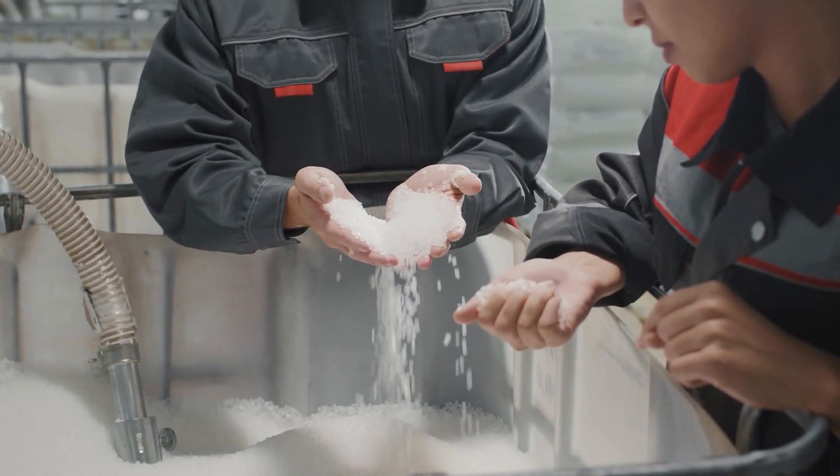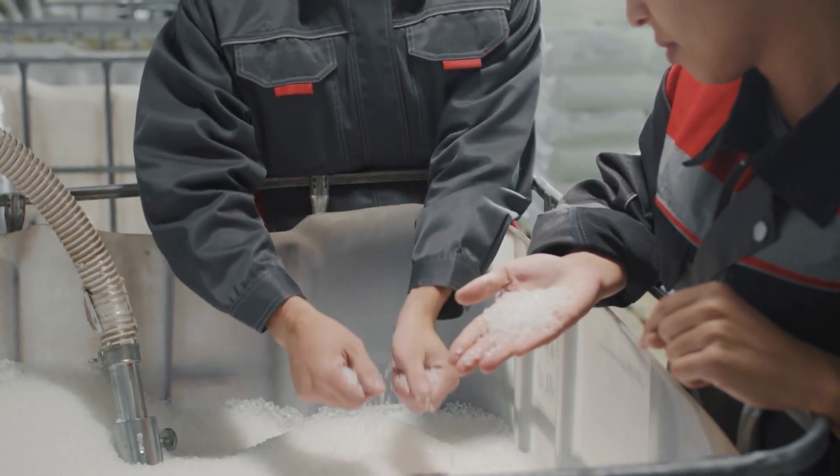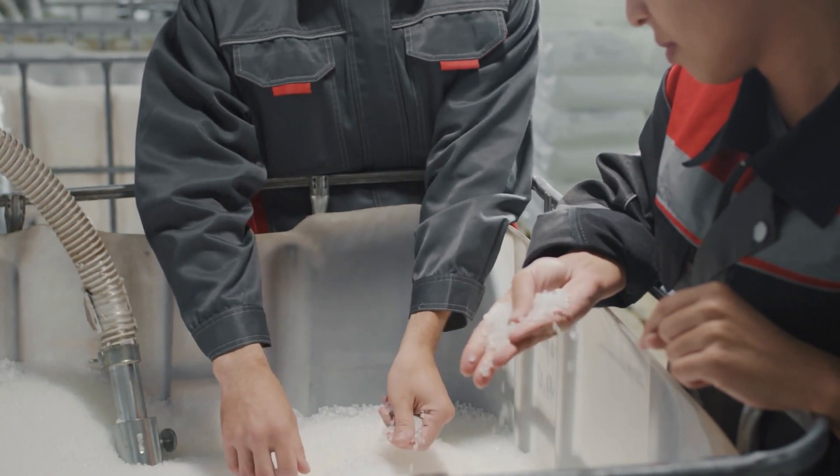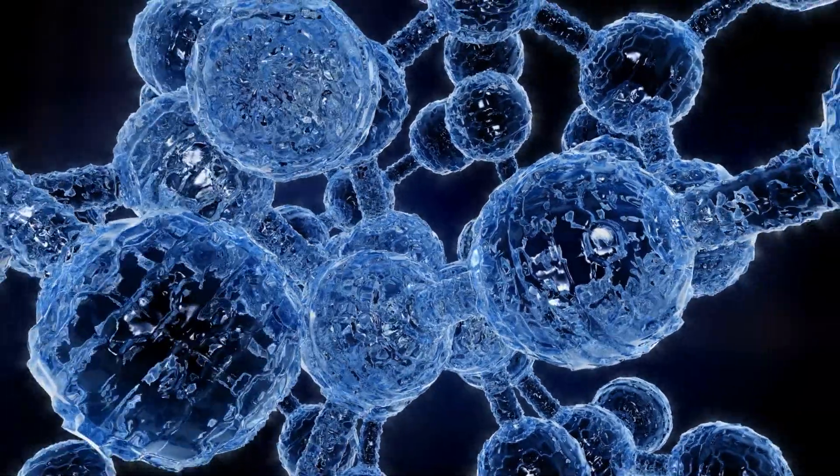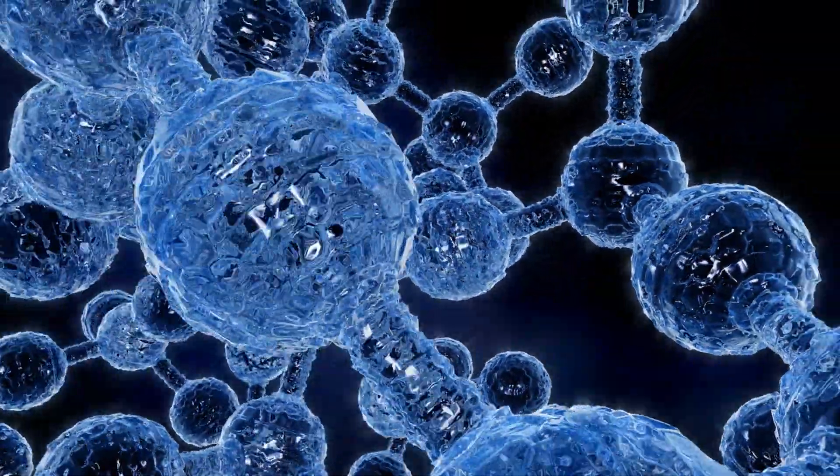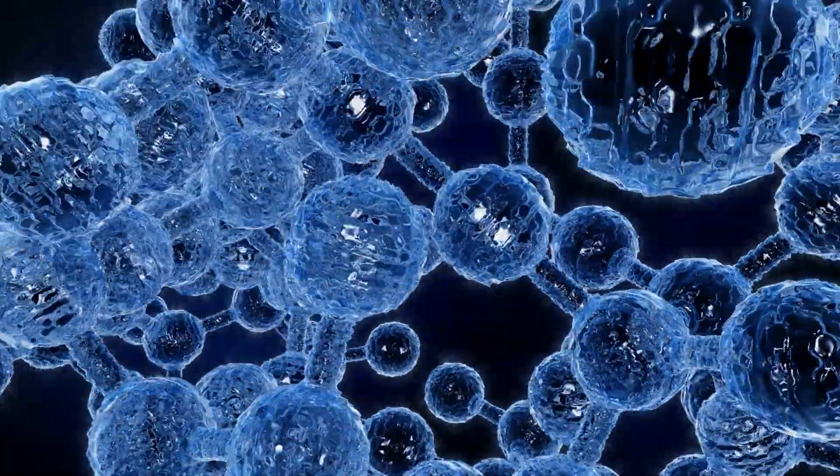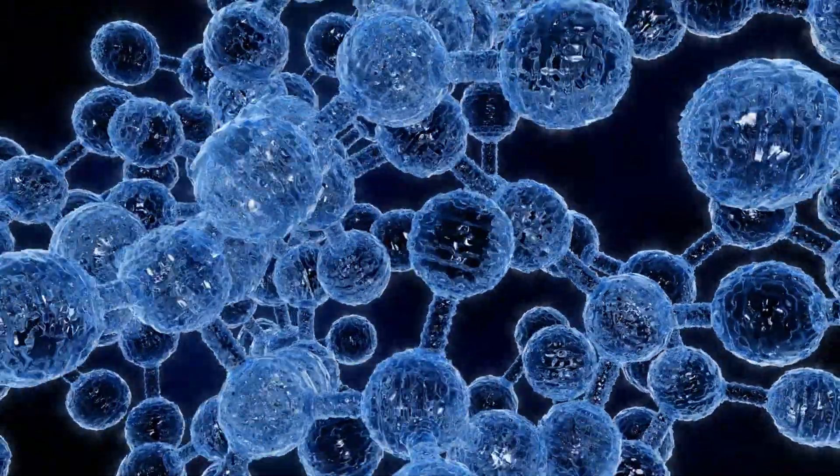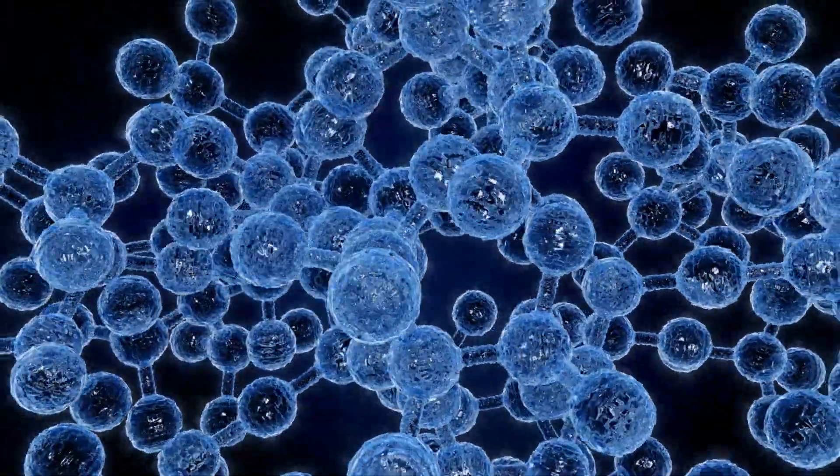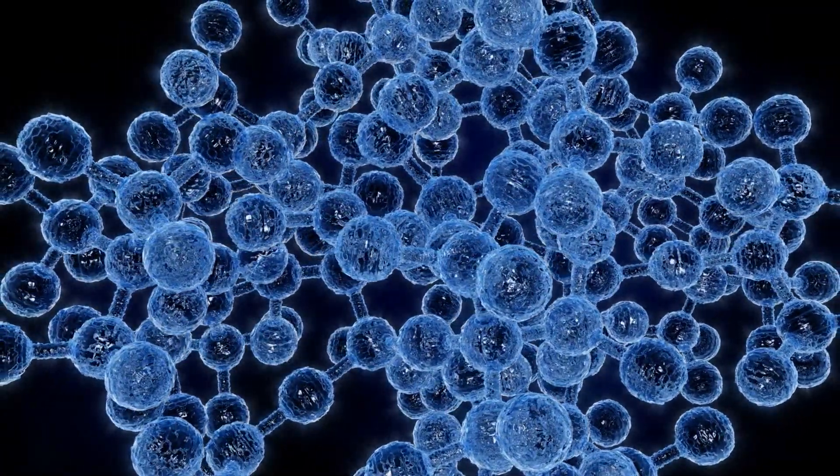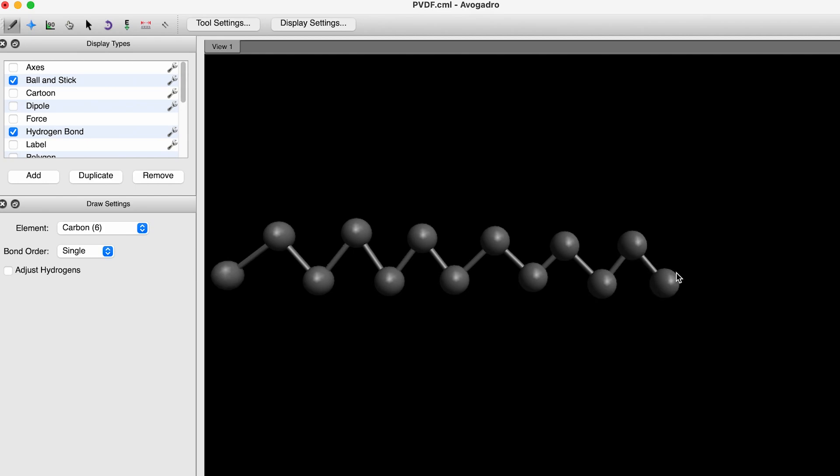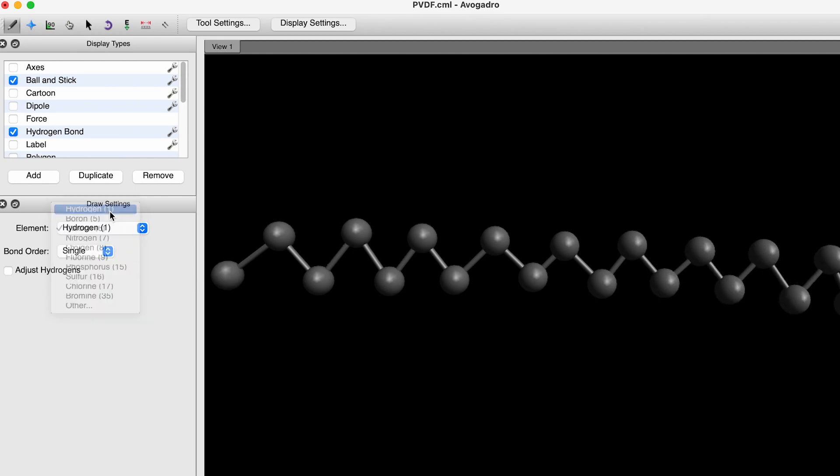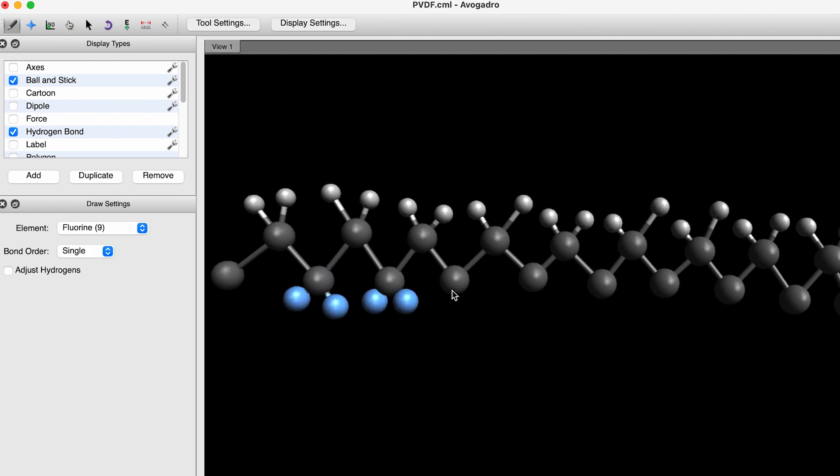PVDF resin has been subjected to high heat experiments to test its thermal stability. It was held for 10 years at 302 Fahrenheit or 150 C, and subsequent measurements showed no thermal or oxidative breakdown in the material. PVDF resin has also been recorded stable up to 707 degrees Fahrenheit or 375 degrees C in short bursts. So as long as you don't get it too hot, you'll be safe with PVDF.